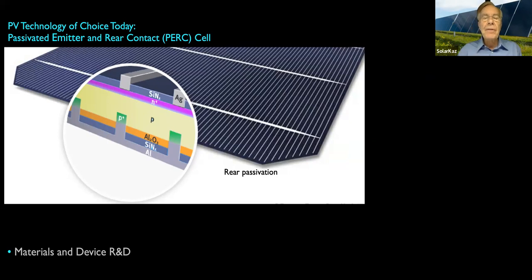So you don't lose them during the process of conversion. The back surface of the solar cell is better passivated. The front surface is better passivated. And so you don't lose these electrons and these positive carriers called holes at these two interfaces. This looks complex, but it's still very, very simple. And if you look at the 190 gigawatts that were shipped last year, most of these were these PERC solar cells.